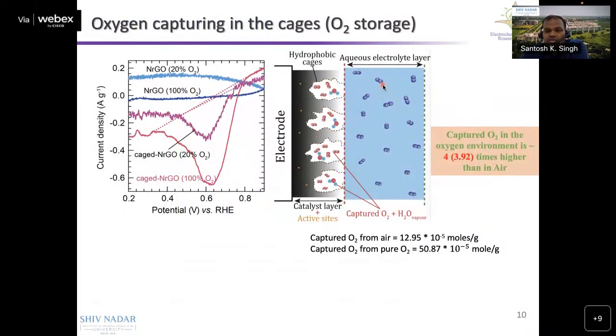over the surface. Next, we tried to quantify how much oxygen can be captured in the cages if the cage structure or hydrophobic structure of the catalyst is able to capture oxygen, and we tried to quantify this using some electrochemical methods. We found that the oxygen captured from air in the hydrophobic catalyst was approximately 12.95 × 10⁻⁵ moles per gram, and with pure oxygen it is 50 × 10⁻⁵ moles per gram, which is almost 4 times higher than that captured from air, which is closely related to the partial pressure of oxygen in air.